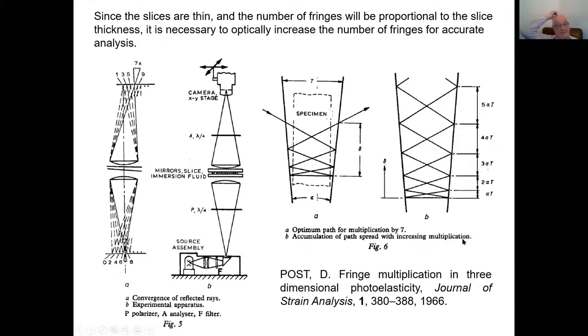How is this done? This is described by Daniel Post in a paper written in 1966, fringe multiplication in three-dimensional photoelasticity. Essentially, things are quite simple in the sense that you are using a polariscope with quarter wave plates and so on. But you are taking a slice which is put in between two partial mirrors. So you have to have light going through these mirrors, but on the other hand, you need good reflectiveness of these partial mirrors, as you are going to have the optimum path of the light going from one plate to the other. So the specimen is in the middle. And of course, here you have some relations by which you can get this multiplication.